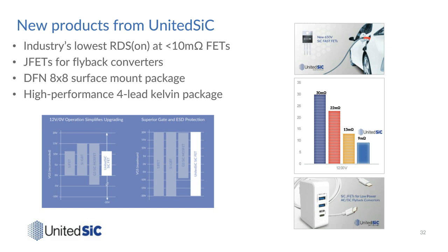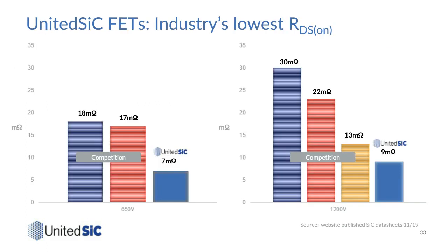So this is what I was speaking about in terms of the lowest RDS(on) parts in the industry. These are in TO-247-4 lead, 7 milliohm at 650 volt, 9 milliohm at 1200 volt, by far the lowest that you can get. All made possible by the fact that you can make JFETs with very low RDS(on)s for a given chip size.